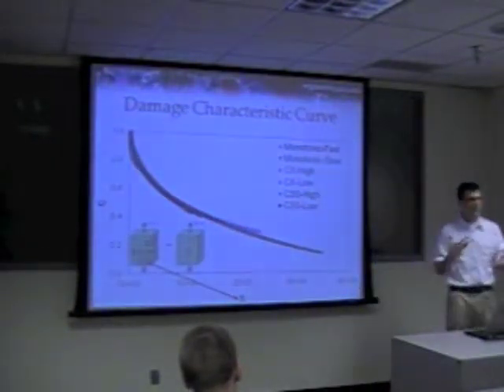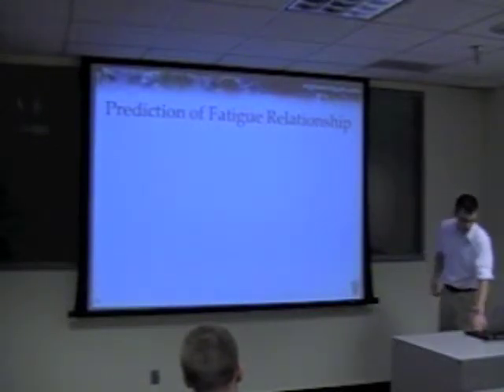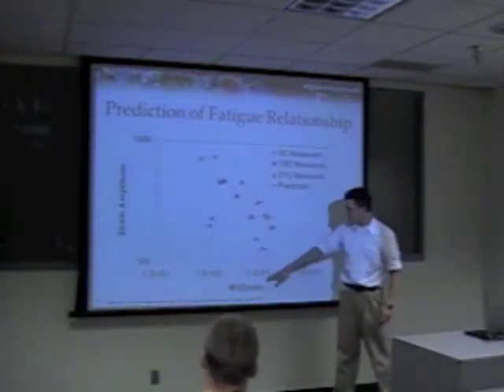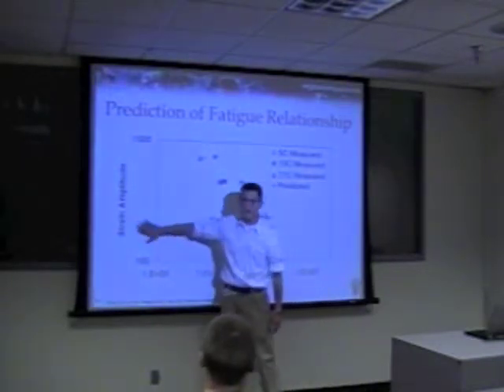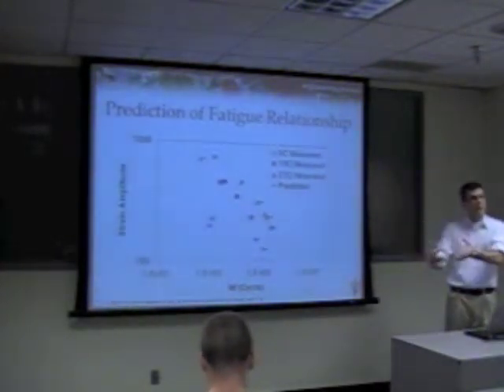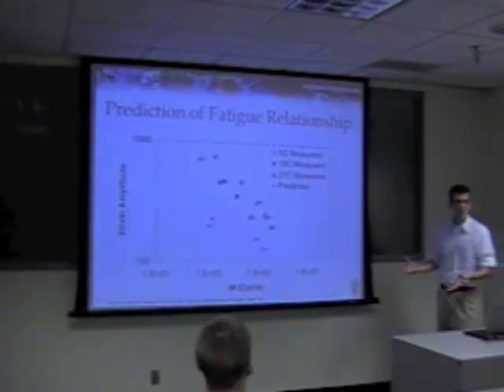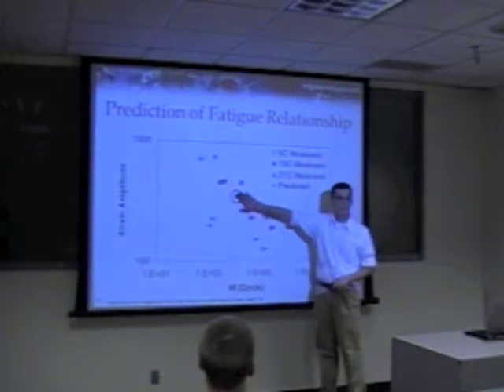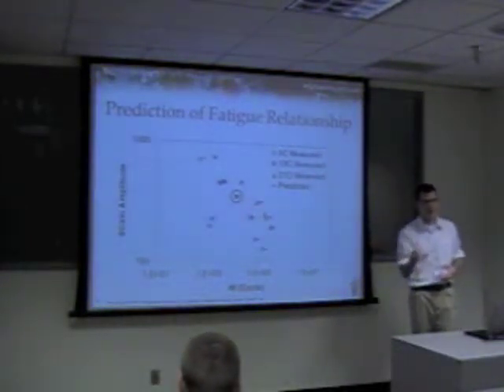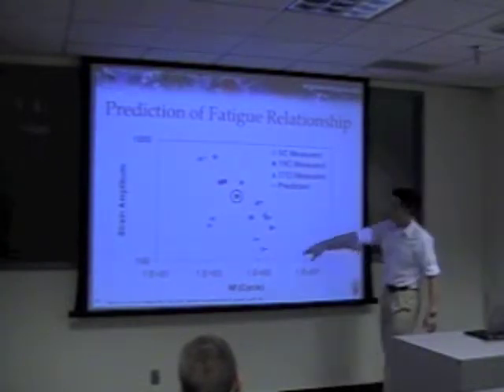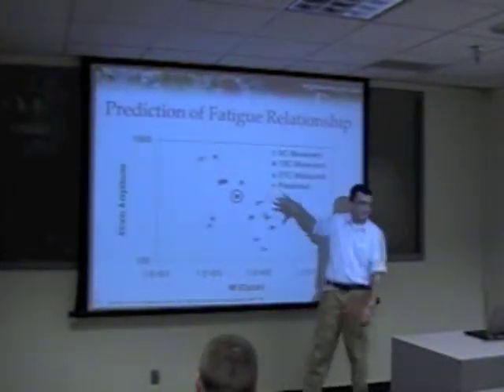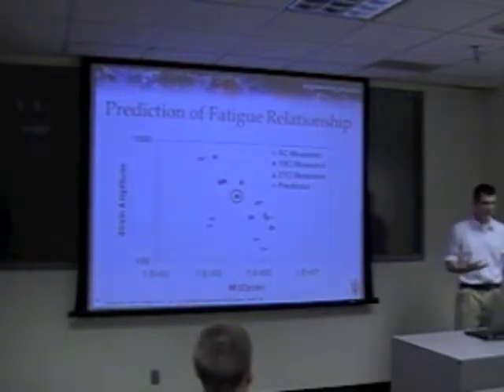That's what we're actually doing with these constitutive material models. The power of that can be seen when we look at a typical strain prediction. Here we have number of cycles on the x-axis, strain amplitude on the y-axis, with measurements and predictions. The key is that the curve is the same regardless of conditions. You take one condition, get that characteristic relationship, and use the constitutive law to predict everything else. All those dashed lines came from running one test — everything else was predicted. That's the power of a constitutive-like relationship.